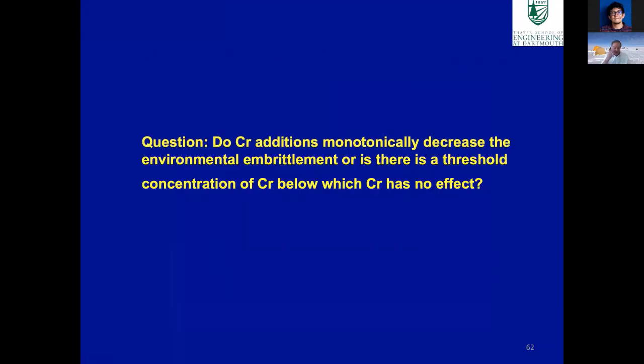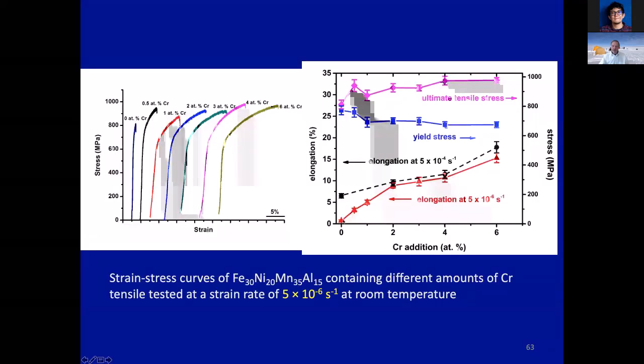One of the questions we had was how much chromium we have to add in order to overcome the environmental embrittlement. So we did some other tests. These are the tests you saw before, the elongation to failure. This is at a slow strain rate, where we see the environmental embrittlement. When we have no chromium, we get variable ductility. If we add chromium, we slowly improve the ductility. By the time we've added 2% chromium, we're getting about the same ductility as when we do a test at the higher strain rate. So by 2% chromium, we've overcome the environmental problem, and adding more chromium just adds to the ductility as a whole. So what is the chromium doing?